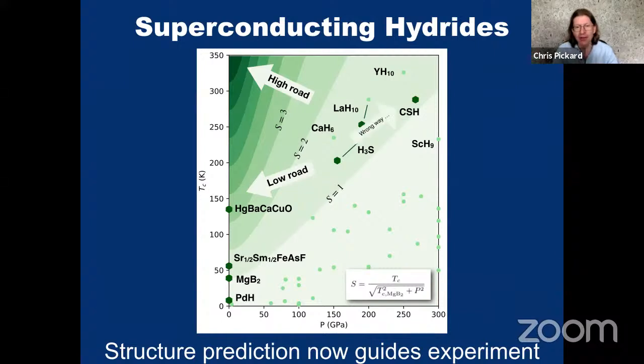But I would just point out that we started at hydrogen sulfide experimentally. We've gone to LaH10 and we've gone to CSH. Not to criticize my wonderful experimental colleagues, but in my opinion, we're going slightly the wrong way. We're not trying to find the highest TC at the highest pressure. We want ideally something that can transform our lives and the possibilities of technology.